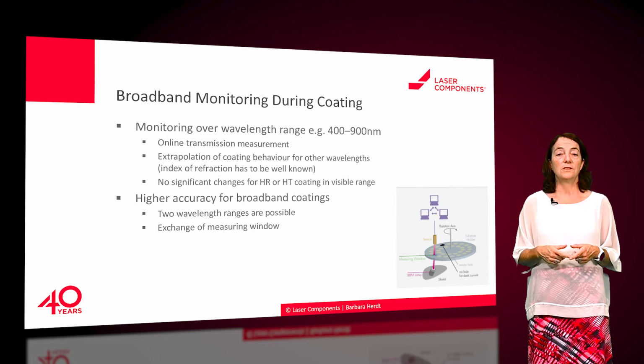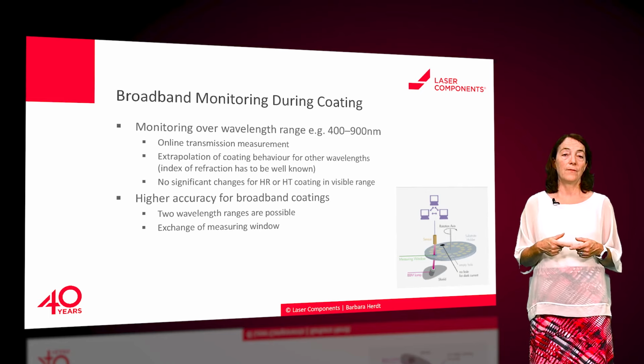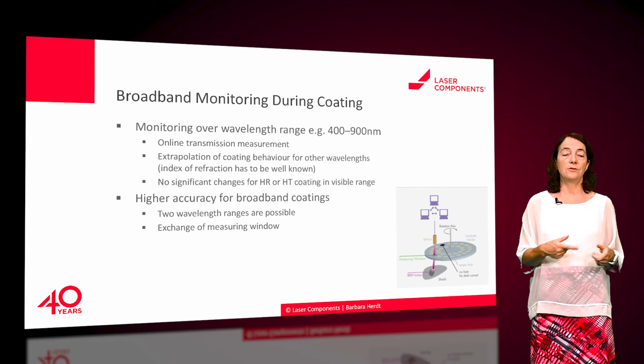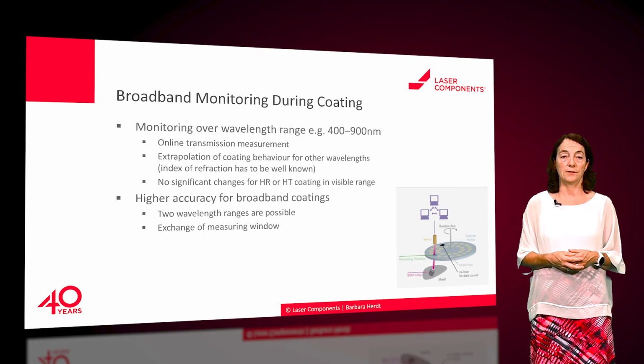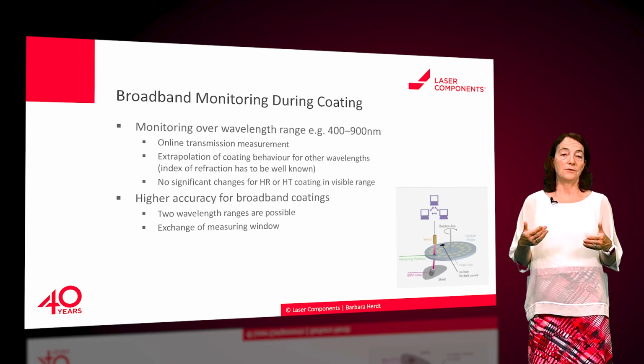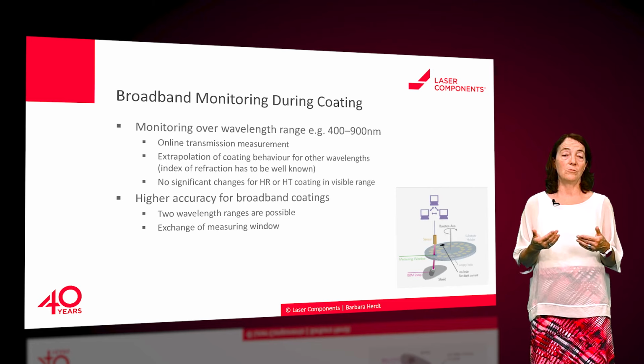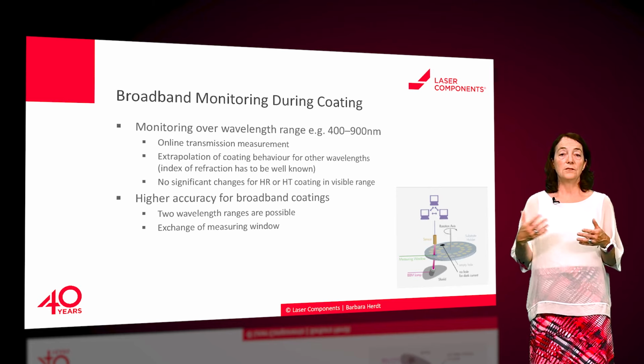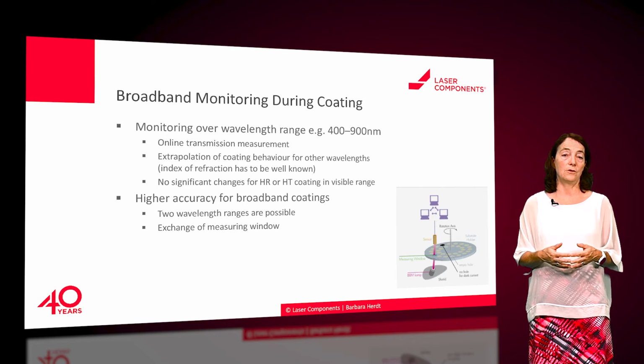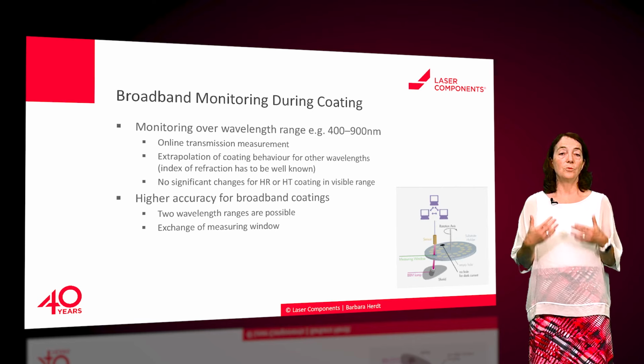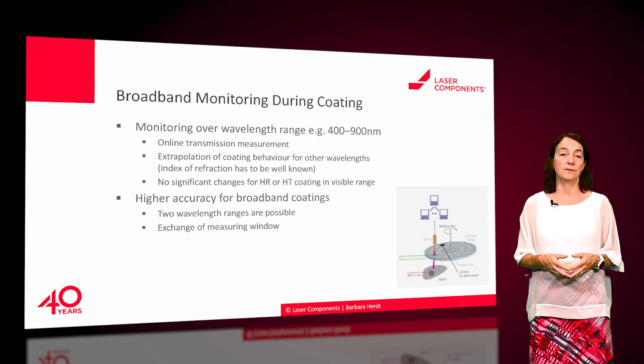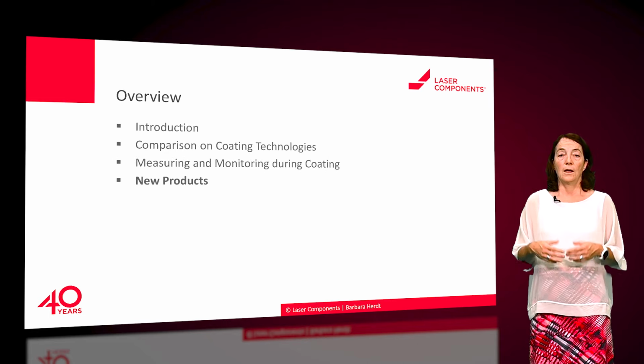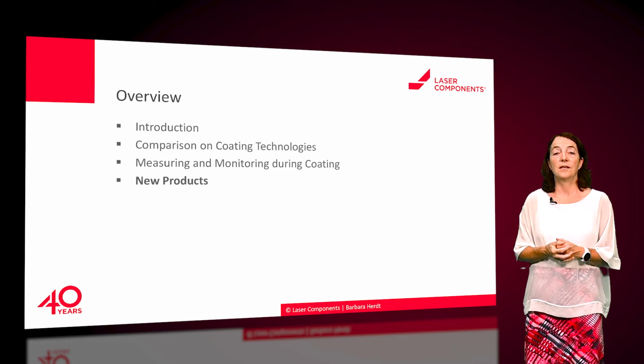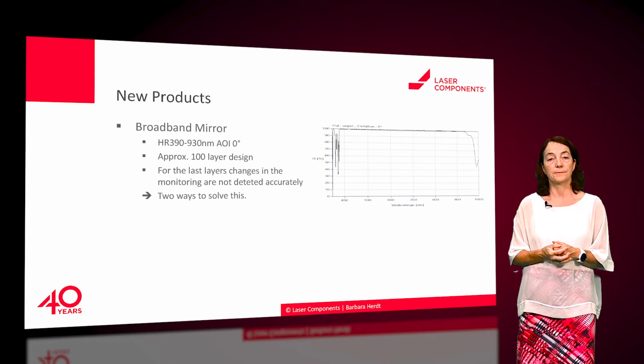One problem with this measuring technique is still if there is an optics with a high reflectivity or high transmission over the monitoring wavelengths. In this case, after several layers, there are no significant changes detected on the measuring window. Thus, the accuracy is not good enough any longer. We have two possibilities to overcome this. I want to explain this with one example on how to solve this.